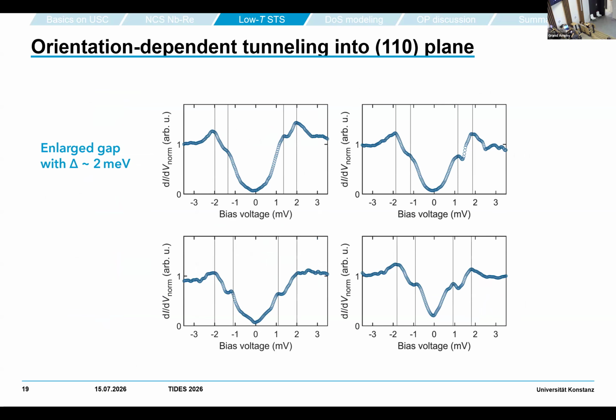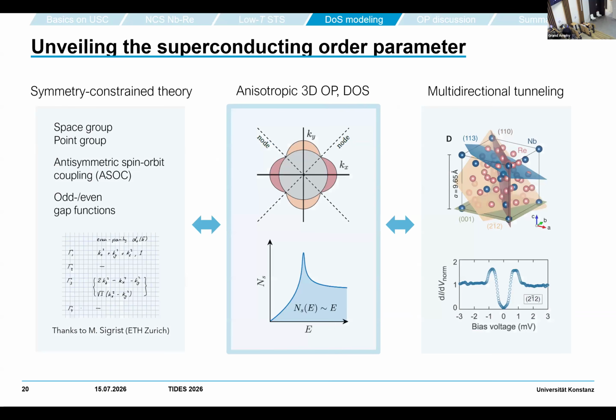Finally, the last plane, this 110 plane, showed features that exist only on that plane. This is something that looks like double gaps, right? Here, marked with these vertical lines, we do see shoulders or even peaks, and where the outer peak, if you want to call it the coherence peak, is your choice, is not at 1, as our typical gap is, but it's more like 2 millivolt. And so this is the spectroscopic zoo that we have to understand.